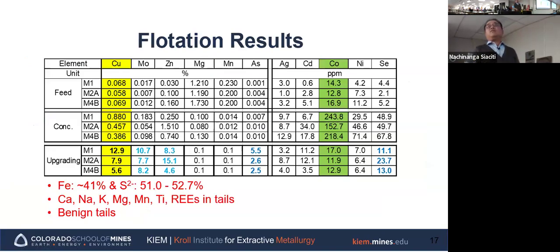So this is the flotation result after the mineral processing from the feed material. This is the feed, and this is the concentrate, and that's the upgrading factor. So 0.07, 0.06% copper becomes 0.8, 0.4, 0.3. So the average is almost 9 times upgrading of the copper concentrate. It's waste, not economic, but if we have a 0.8% copper resource, I think we can process it and get a good profit out of it.